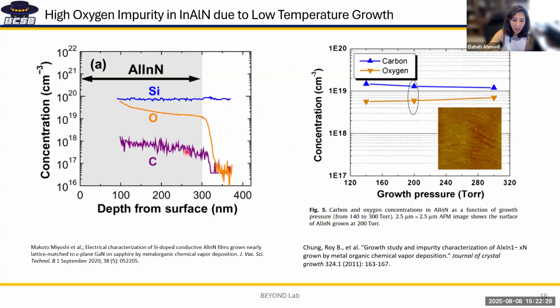We were interested to see if this behavior changes if the barrier is different. But one issue with indium aluminum nitride is that this data is on MOCVD material. Because it needs to be grown at lower temperature to incorporate indium, the oxygen incorporation is very high, and oxygen is basically N-type, a shallow donor in nitrides. And so this would cause issues in devices.